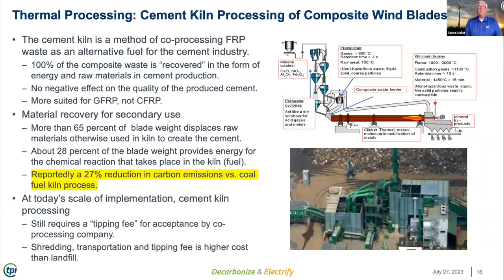More than 65% of the blade weight displaces the raw materials in the kiln. So we're displacing one for one mined materials and reducing the embodied energy necessary to build the kiln. And studies have shown about 27% reduction in carbon emission versus kiln processing with coal. Today's implementation still requires a significant tipping fee. I've seen those fees range anywhere from $400 to over $500 per ton, but it is a viable approach. Still emits carbon into the atmosphere, but it offsets that same carbon that would be used to make that volume of cement.